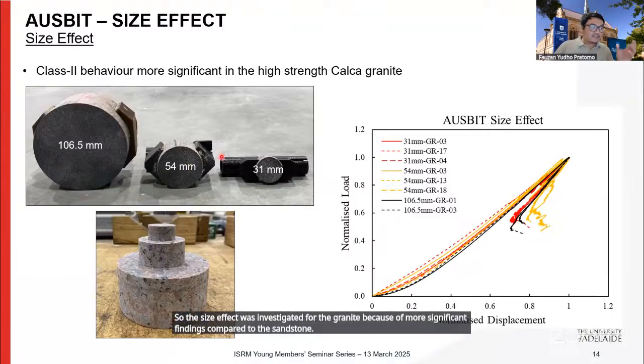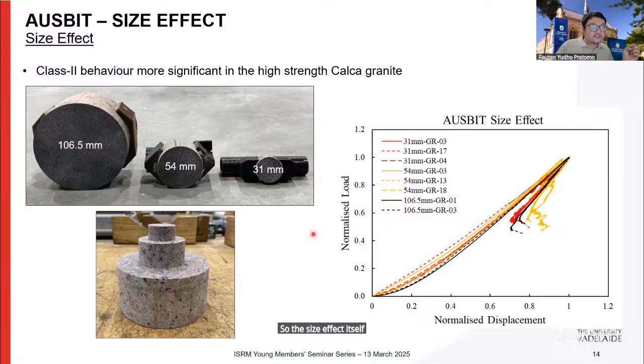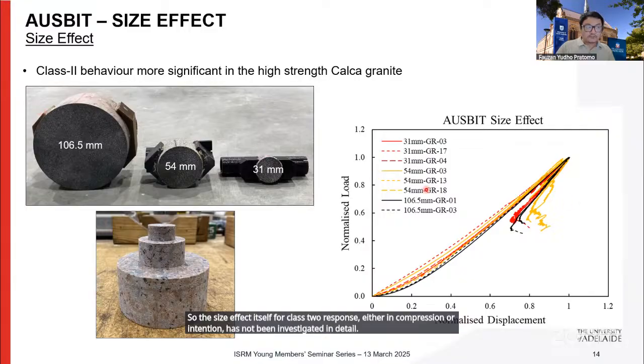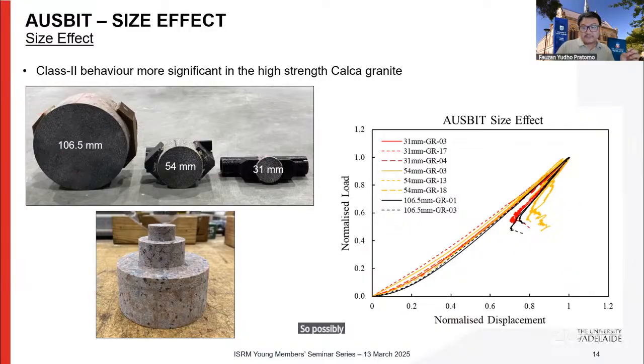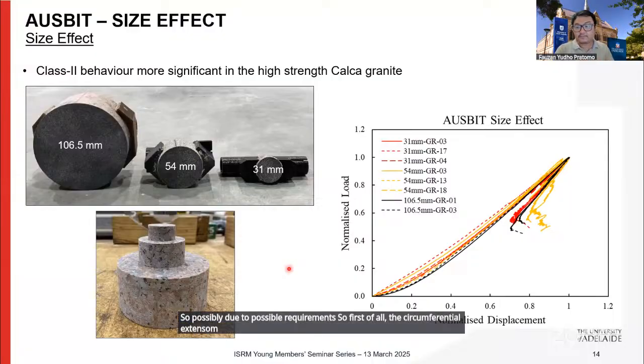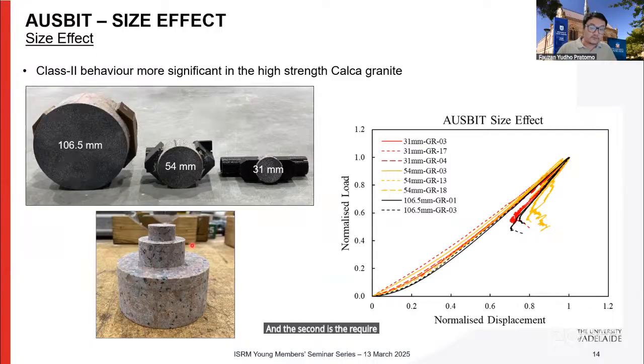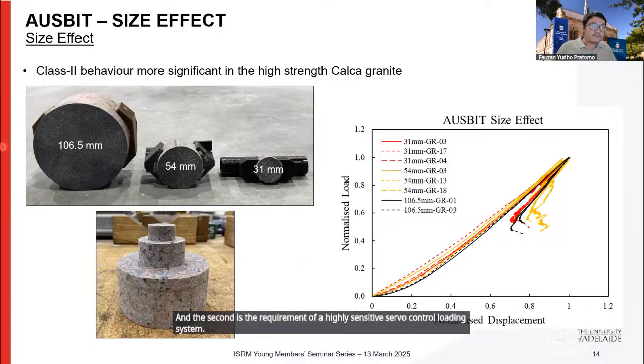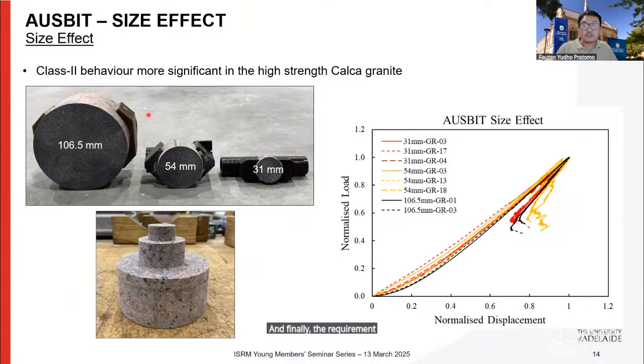The size effect itself for class 2 response, either in compression or in tension, has not been investigated in detail, possibly due to certain requirements. First of all, the circumferential extensometer by ISRM is usually for specimens less than 100 millimeters in diameter. The second is the requirement of a highly sensitive servo-controlled loading system. And finally, the requirement of a very large loading capacity.